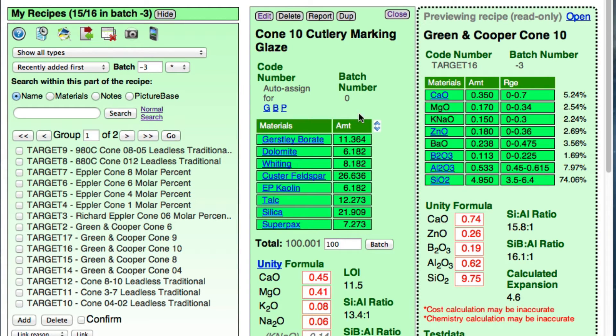These are materials, and these are oxides. You'll notice Insight Live is trying to calculate a formula for this limit formula because it's finding some of these oxide names as secondary names for materials available in pure form. But we won't pay attention to that. Materials decompose to oxides during firing, and these oxides arrange themselves into a glass structure as the kiln cools. Stable structures happen when their relative amounts are within some reasonable proportion — and that's what's expressed here. These limits are about what a strong, wear-resistant glass looks like.